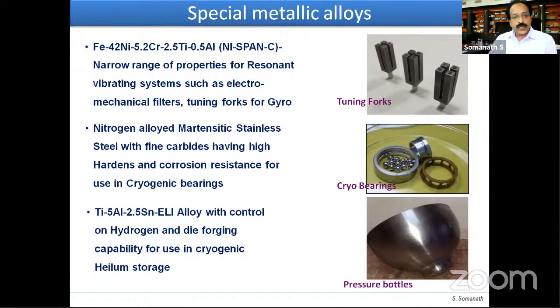Another development is nitrogen alloyed martensitic stainless steels with carbide dispersion, developed for cryogenic applications. The titanium 2.5 Sn ELI grade alloys are for control of hydrogen, required for cryogenic applications for helium storage. So these were some of the typical alloys which have been developed after great effort.